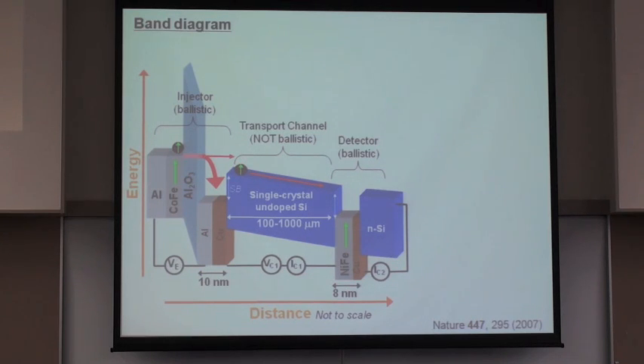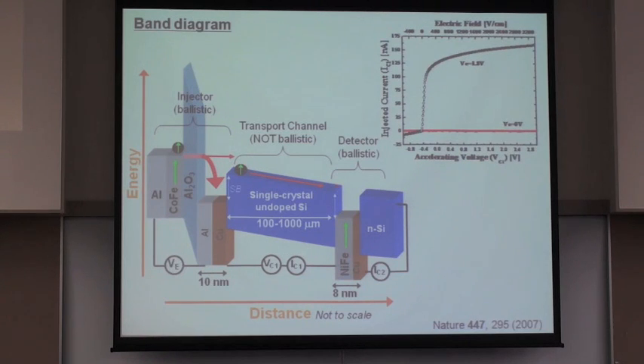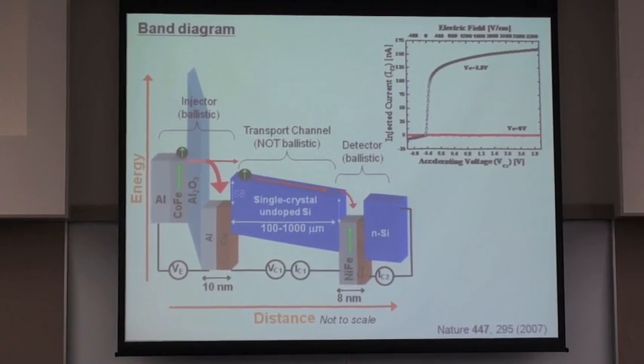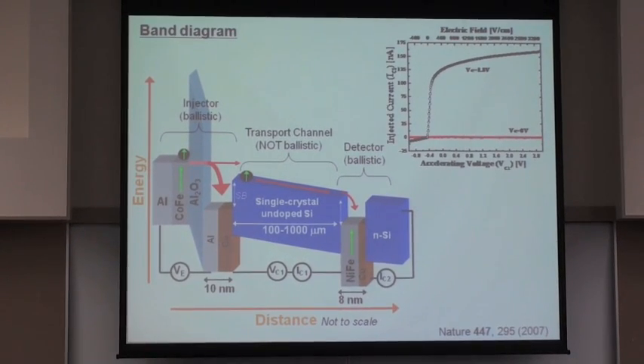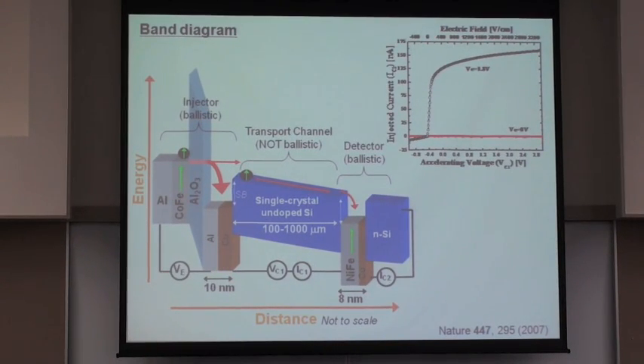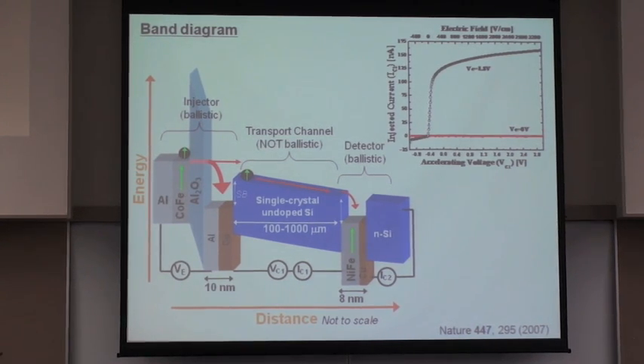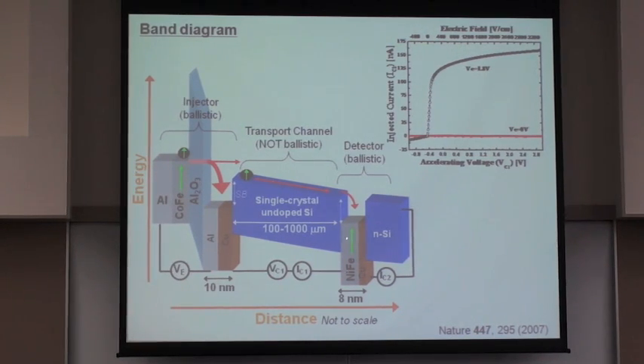Okay, so that's how we achieve the injection. How do we detect these electrons? Well, these electrons are at the detector side, ejected from the conduction band into a ferromagnetic contact. Now, keep in mind, once again, these electrons are coming over a Schottky barrier. It's as if they're jumping off a cliff. And so they initially have a very high kinetic energy. So they're once again hot electrons, but they're hot electrons not in a non-magnetic anode. Here they're hot electrons in a ferromagnet.